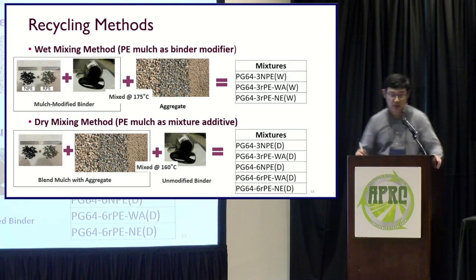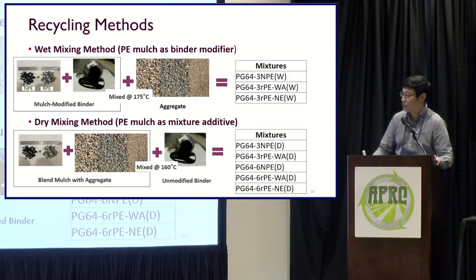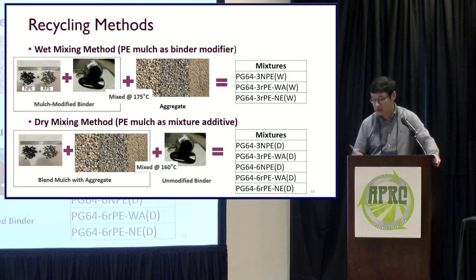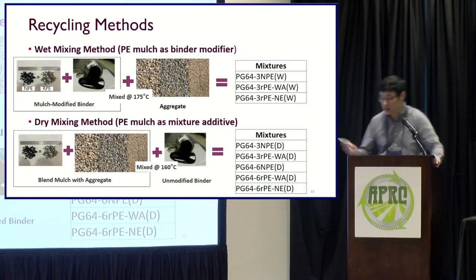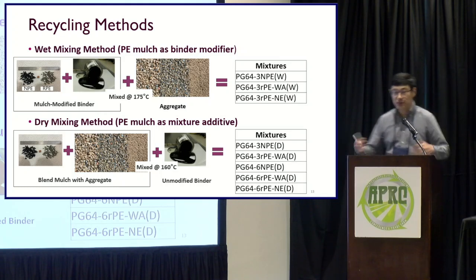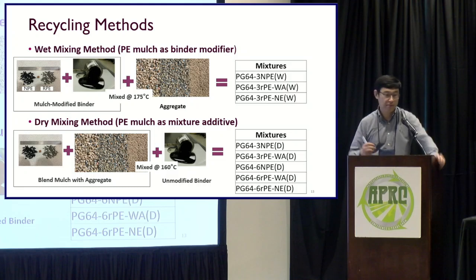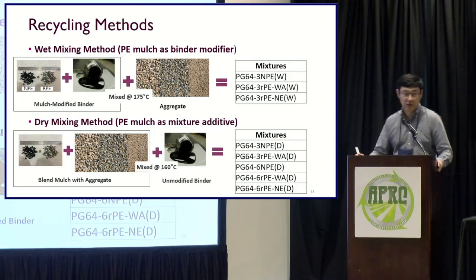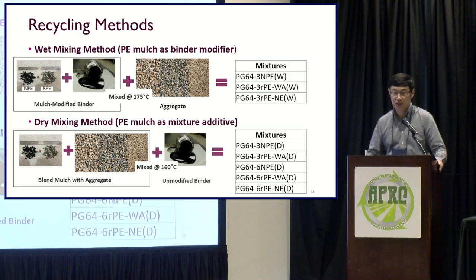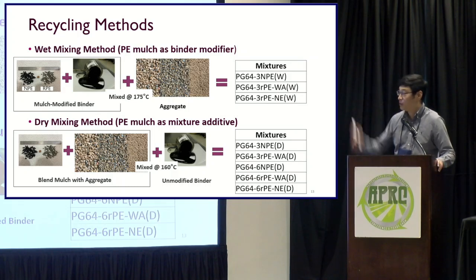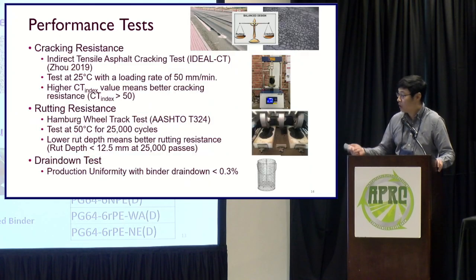Well, for the dry mixing method, we blend the PE mulch as a mixture additive. So we first blend the PE pellets with the aggregate and then blend with an unmodified binder. So during this process, the mulch can be partially melted into the binder, okay? But it's hard to know what the percentage of the melting into the binder is in the dry mixing. But in this way, we use a PE mulch as a mixture additive. So we create 5 different mixes, and we use a 3% plastic, and also we even use a 6% plastic in the dry mixing.